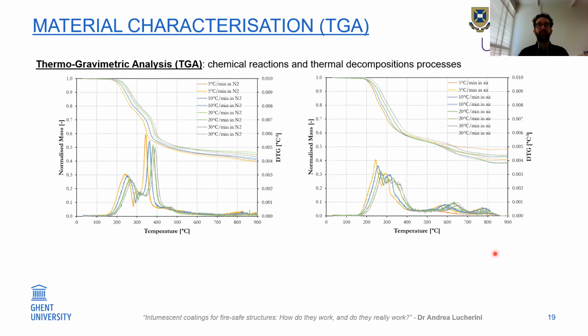So how to start the research? The first step for my research was to carry out TGA, which stands for Thermogravimetric Analysis. This takes a little bit of the coating, a few milligrams, like 10 milligrams, and you put it in a furnace. In the furnace, there is a very accurate scale, and you can track, here the curve from 0 to 1. You can imagine from 0 to 100%, how the mass of the coating decreases at different temperatures. This is the case of N2, so in a nitrogen environment, so no oxygen, and this is the case of air.